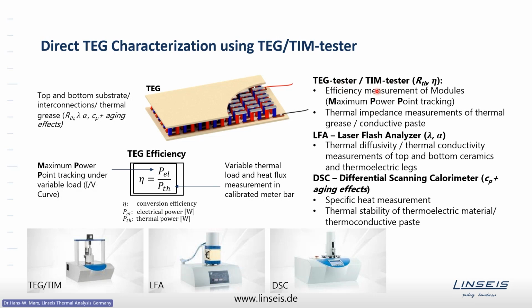With a TEG tester in the so-called TIM tester mode, TIM tester standing for thermal interface materials, the thermal impedance of materials may be analyzed, for example, for thermal greases and conductive pastes, which are used to build up thermoelectric generators. The laser flash analyzers may also not only be used to measure the thermal conductivity of the legs, but also of the ceramics used to build up a thermoelectric generator.